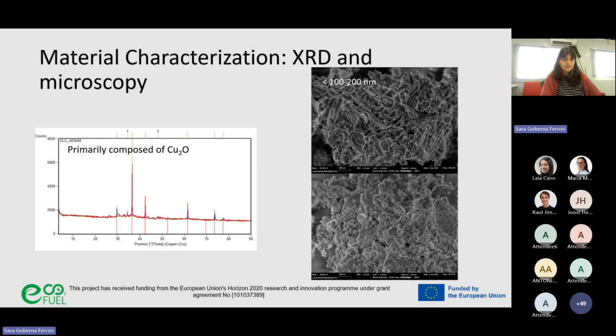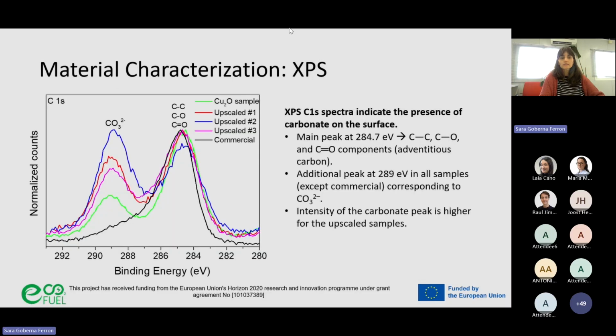Regarding the material characterization, again, we use microscopy and XRD. By the XRD pattern, we can confirm that the bulk of the material is primarily composed of copper-1 oxide, cuprite. We didn't detect any other peaks by XRD. The microscopy image shows that the material is composed of homogeneously distributed particles with a size between 100 and 200 nanometers. Now, we also used XPS to characterize the surface of the material.